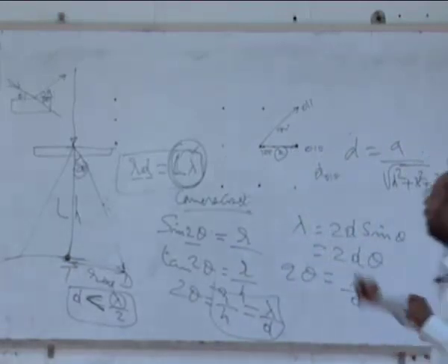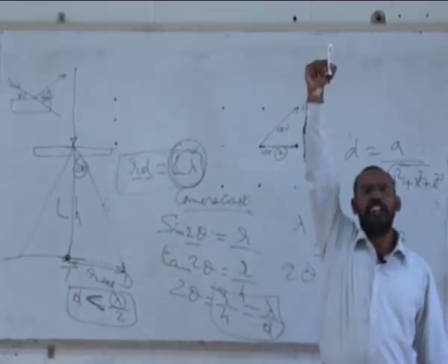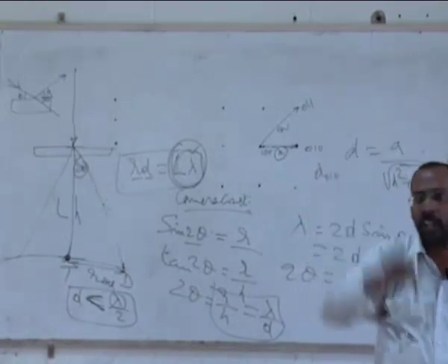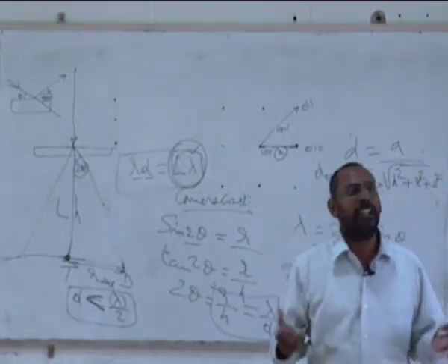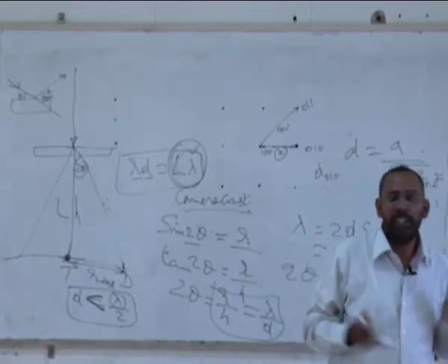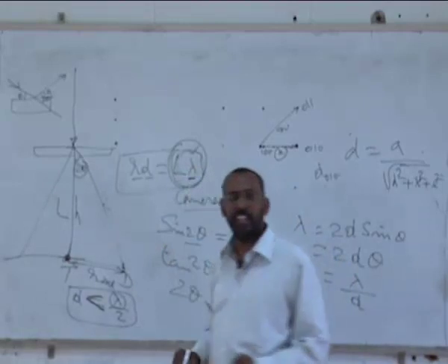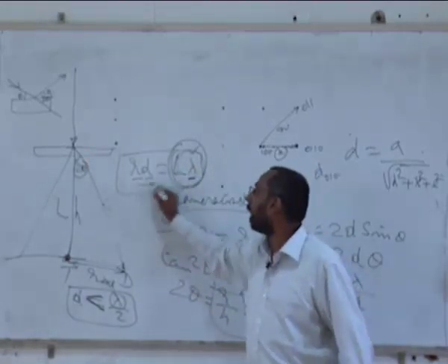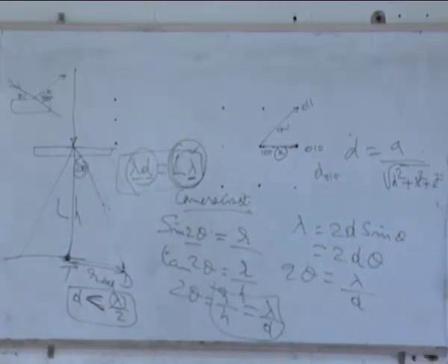are not so easy in this, because the lambda that I am using, though I say 100 kV microscope and there is one lambda, most of the time the lambda that falls on the sample is not really monochromatic. It has some range. And as a result, when there is a range here, obviously this calculation will have a problem. Okay? So as a result, you have some inaccuracies. Of course, that is where aberration corrections are coming into picture.